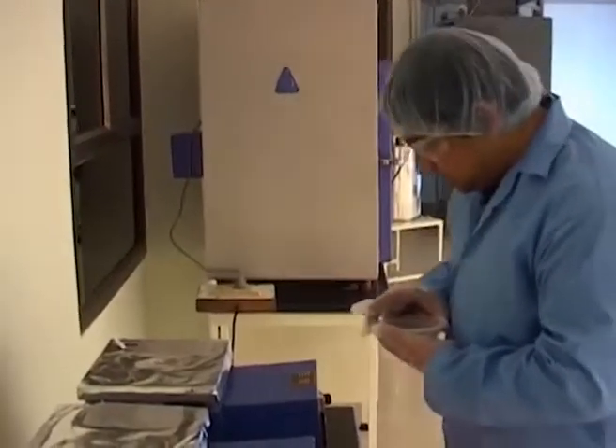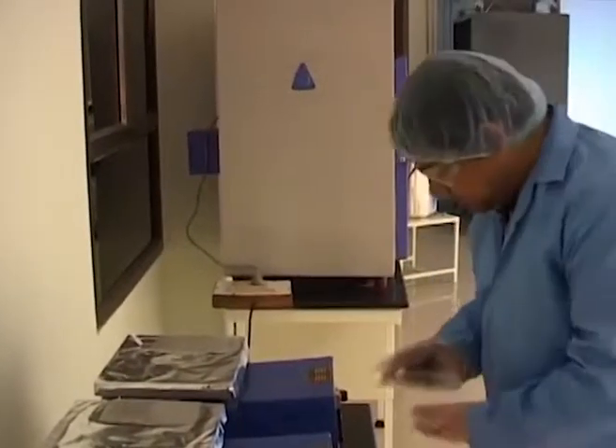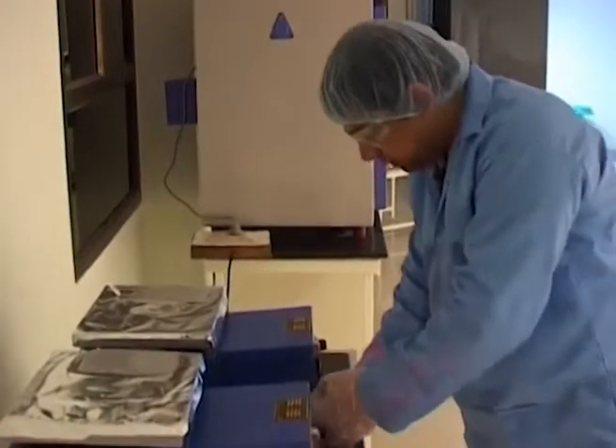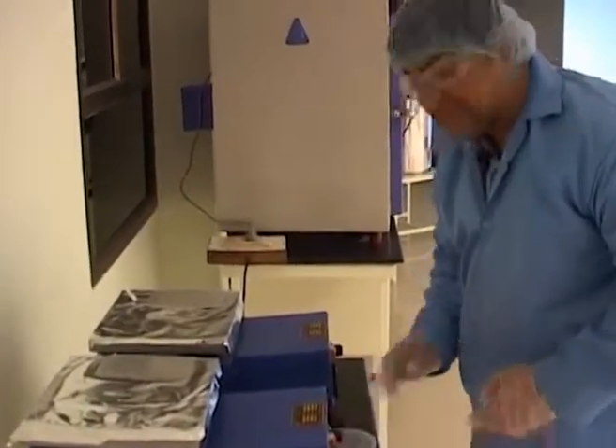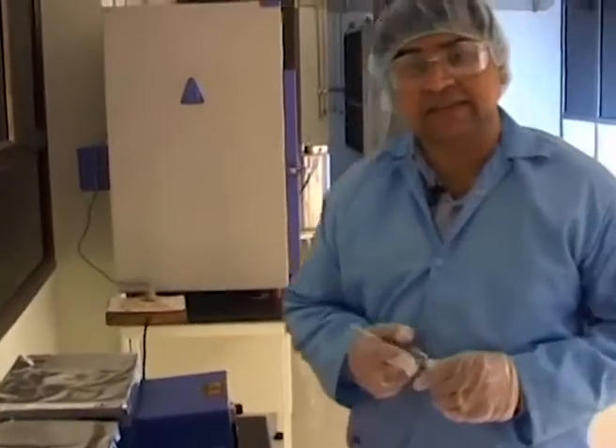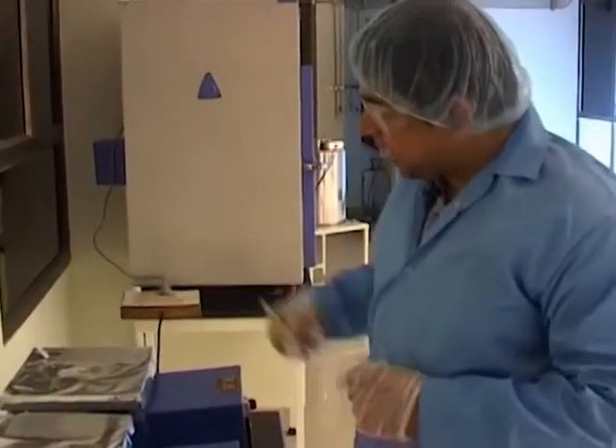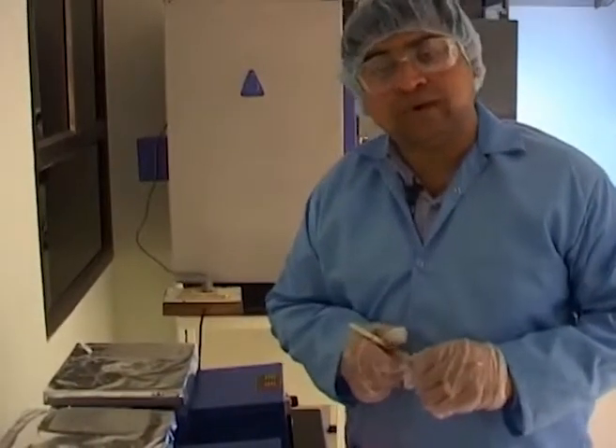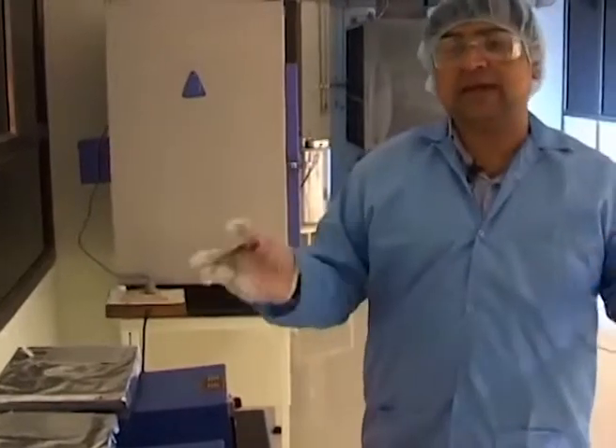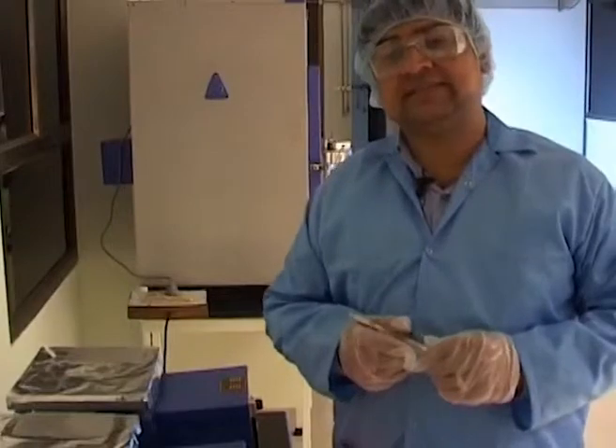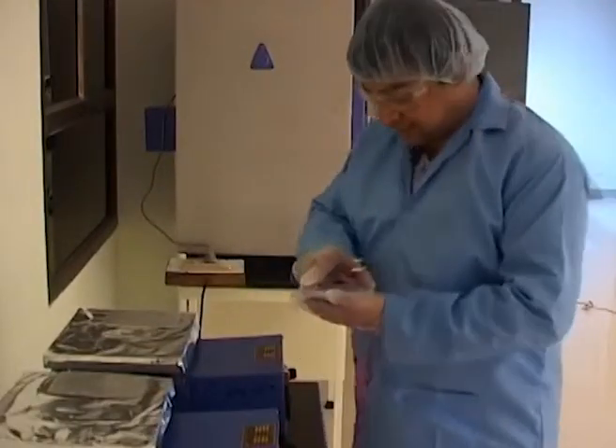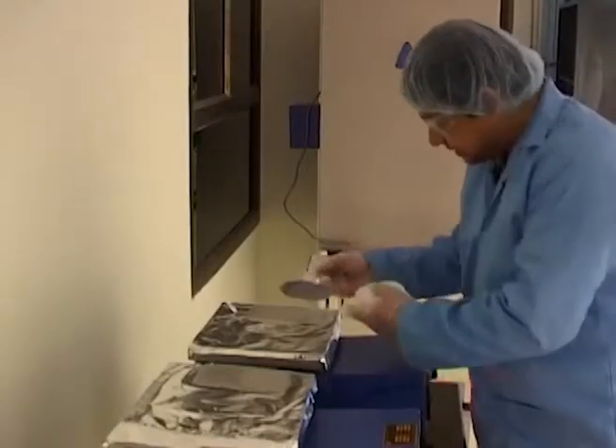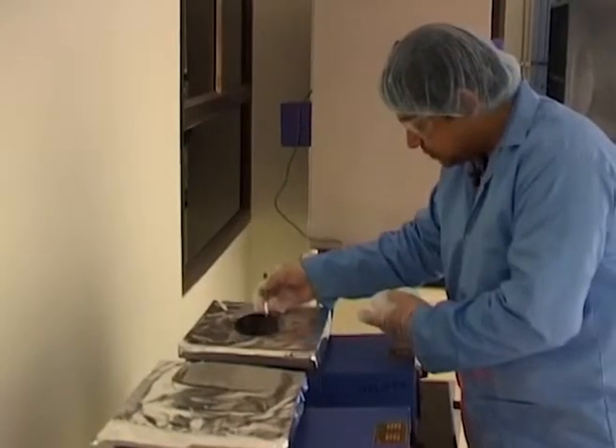So essentially we will hold this for some 5-6 minutes till it equilibrates back to the room temperature, and then we will use the second heating step of 95 degrees and put this resist back again for about 5-6 minutes for the full curing action to take place, after which we will do the UV exposure of the resist using the mask.